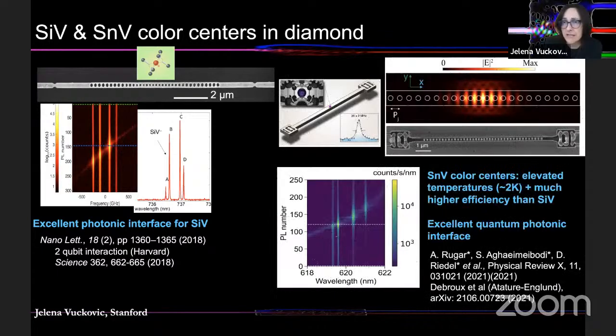But the state of the art is that excellent quantum photonic interfaces exist for these color centers, and interaction between 2 qubits in the same resonator has been demonstrated by the group of Misha Lukin and collaborators at Harvard. More recently, we started looking into tin vacancy color centers, which is exactly the same geometry of a color center as silicon vacancy. You have 2 missing carbon atoms and an extra tin atom inserted here.